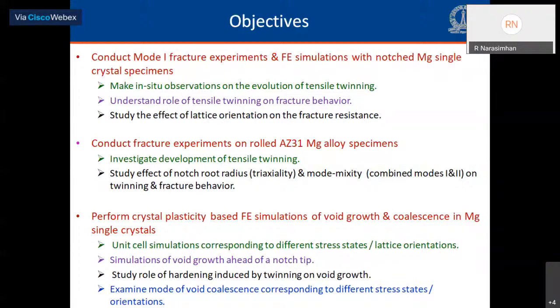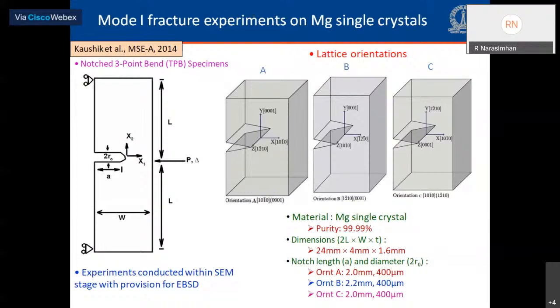And the last objective, which I'll be describing today, is some finite element simulations of void growth and coalescence in magnesium single crystals. So here we have carried out simulations using unit cell models as well as void growth and coalescence ahead of a crack tip in the fracture process zone. Let me first show some results from our fracture experiments using magnesium single crystal specimens. And these were conducted using three-point bend specimens, which were tested inside a scanning electron microscope with provision for electron backscattered diffraction to make in situ observations.